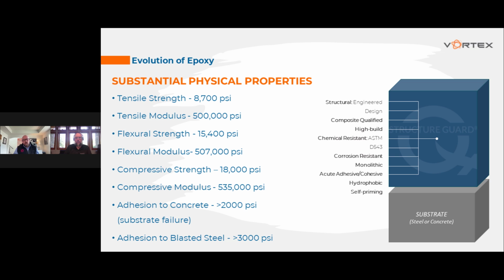I will note though that these types of epoxies can continue to cross-link and harden and get to their full cure within 24 hours. So 4 hours you can return to service. 24 hours we would expect that to be absolutely fully cured. But the nice thing about epoxies, and this is inherent in an epoxy technology or chemistry versus a polyurea or polyurethane, is our epoxies are hydrophobic, right?